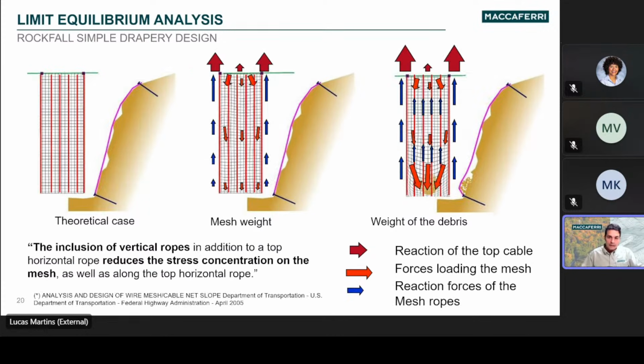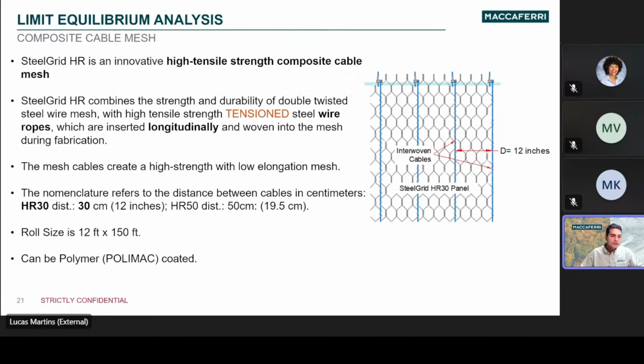This is an effect that is addressed in the WashDOT guidelines, and it suggests that the introduction of vertical high-strength steel cables into these systems, either woven into the mesh or connected to it, will help control deformation under load and allow the system to mobilize the full tensile strength capacity of the mesh. And here is where I present to you the SteelGrid HR. SteelGrid HR is a composite cable mesh, meaning that you're